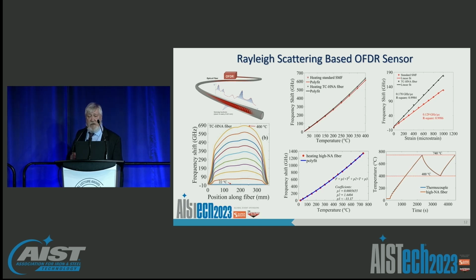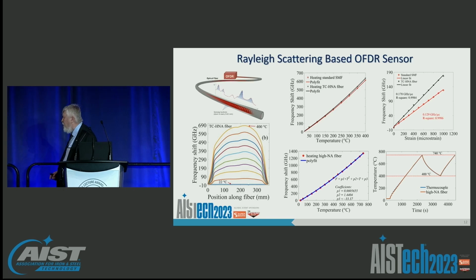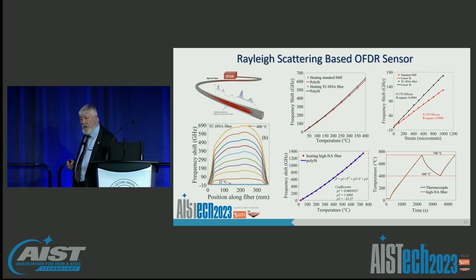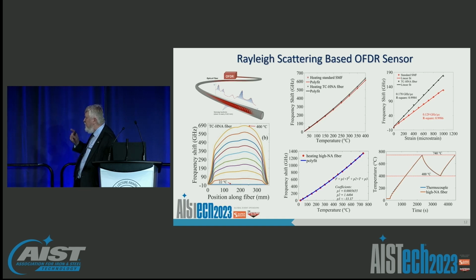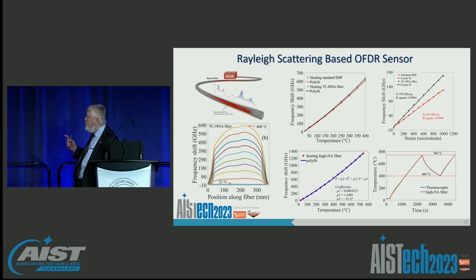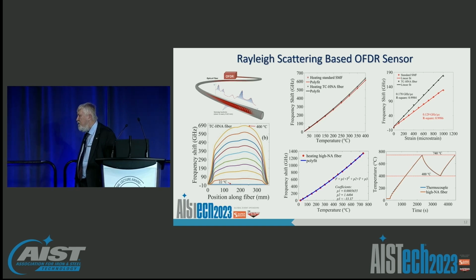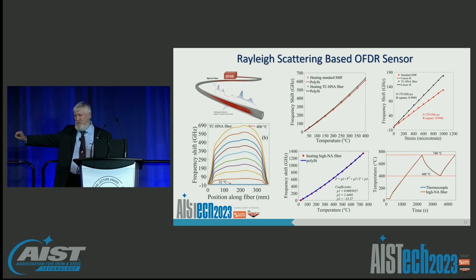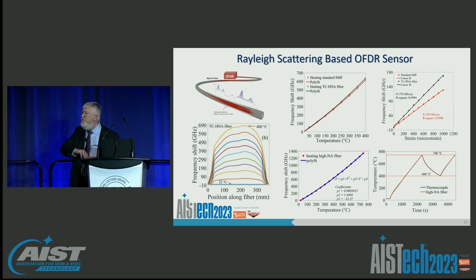So you'll notice here, if you look at the bottom right, you'll notice that there's a plot going up and down in temperature, superimposed on it a thermocouple, right? And you can get an idea of how accurately these things trace and predict the temperatures based on their frequency shift. But that comparison is a little deceiving, because what you also get is the information on the bottom left, which is the full temperature distribution along the length of the fiber. So running one fiber through your furnace or in an environment will actually give you the whole profile. And that's really exciting stuff.